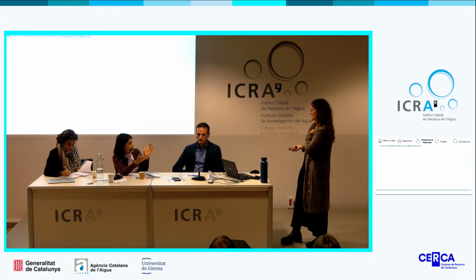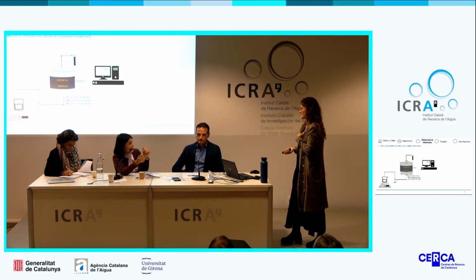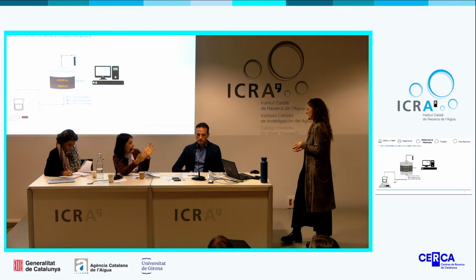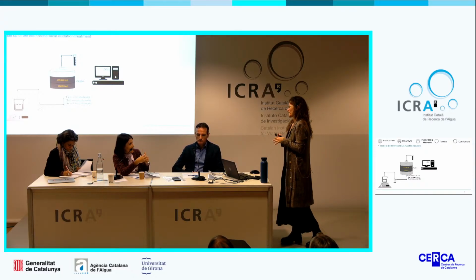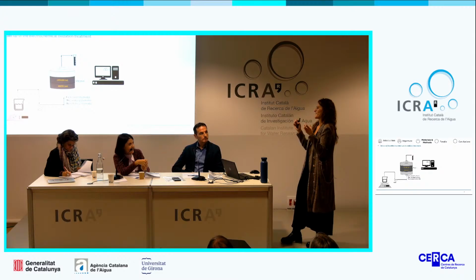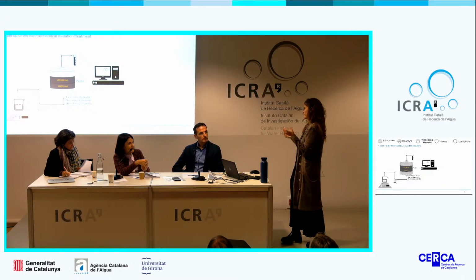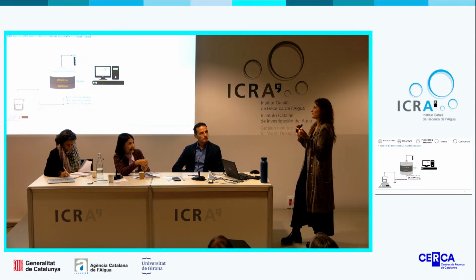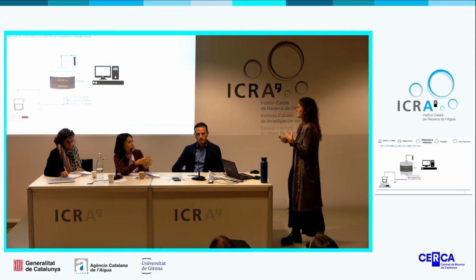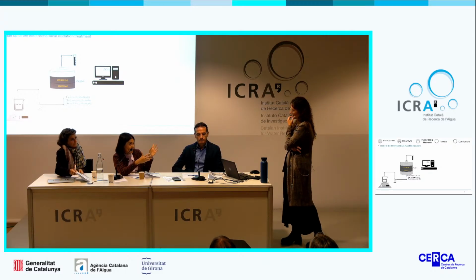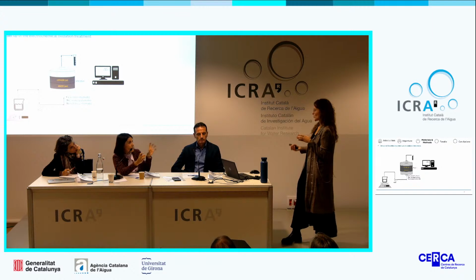Yes, that's why we also have... We are using stainless steel for this current feeder. We are using stainless steel because it's a kind of low-cost material, which is not corrosive. Which is your real electrode, the stainless steel current feeder, or your sponge electrode? This current feeder is in contact with water.